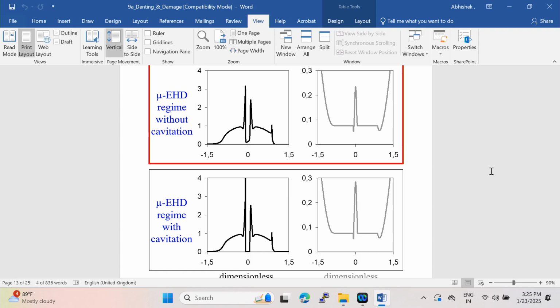Okay. Then you can have that. It's quite typical for depths from a few micrometers. You can typically have this situation. You can see the dent, and you have no cavitation in the vicinity of the dent.